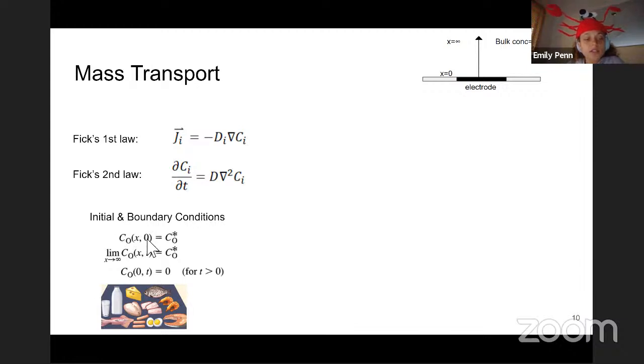So looking at our initial and boundary conditions, first we have our initial condition. So at time 0, everywhere in the solution, the concentration is C_O star. Then the second two equations are our boundary conditions. So as x approaches infinity, the concentration at all times is going to be C_O star. And then our second boundary condition is that at the electrode surface at all times, the concentration equals 0. So that's the particular case that we're looking at here, where you're using up all of your reactant at the electrode surface, so the concentration is 0.